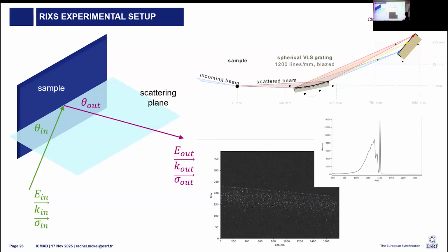But if we integrate it horizontally, we can see the elastic line appears. We have two DD excitations that are trapped in here. There's a PD excitation, and then there's a large band of charge transfer and fluorescence that sits behind everything.